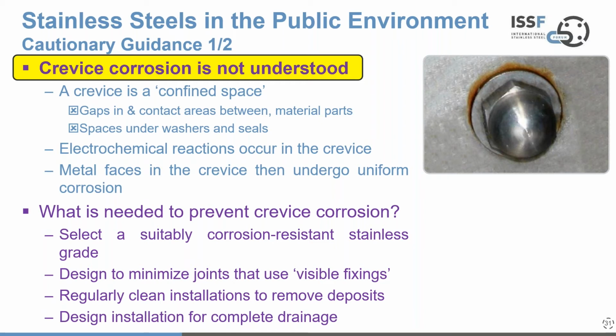Furthermore, it's important to design to minimize joints that use, as in this example here, visible fixings. The more you can do away from them, the more you eliminate crevices. Regular cleaning of installations will remove deposits, because the deposits are part of the process here. So deposits, fine particles get into these crevices, but also design the installation for complete drainage, because simple condensation will start to cause a problem in this situation, because it will drag deposits into those crevices. So it's important that these things are understood and designed out.